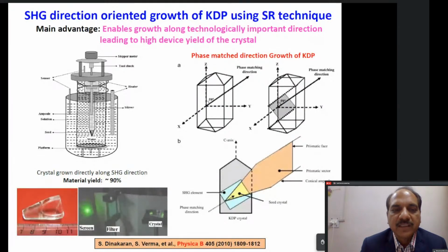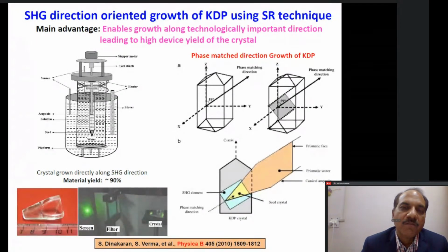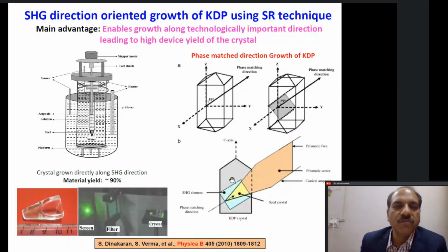So this was the first report which appeared in literature which shows that we can directly grow crystals in the phase matching direction. Usually what we do is we grow a crystal in its natural morphology. This I'm talking about growth from solution, right? So in the previous two slides I had talked about Czochralski growth, then I talked about Bridgman growth. Now I will be talking about results from solution growth, right? So usually when a crystal is being grown from solution it takes a natural morphology, right? But sometimes what happens is when you have to take out a device element from it, the usable volume of that crystal which is finally being used for device fabrication is only a few percent of that crystal.